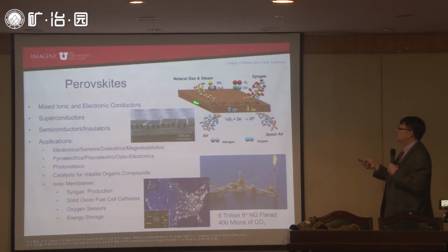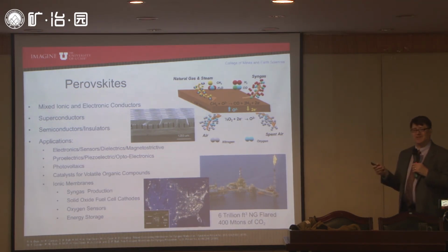So you create these membranes that operate at relatively high temperatures in this fairly hostile environment, because it's reducing over here, oxidizing over here. So this material has to be stable, and ions have to be able to conduct through it, and it gets very warm. It's about 900 degrees C perhaps. So it has to be a very robust material.